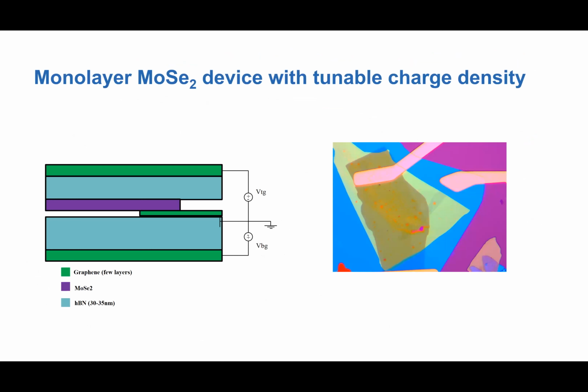Okay, so now an optical picture of the simplest device one can imagine. This is essentially a monolayer with top and bottom graphene gates. And we also have a graphene layer to contact the TMD. TMDs have large Schottky barriers, so it's very difficult to do transport with these. But if you have a graphene contact, you can use it, by changing the gate voltage, to control the charge density. The idea is that by using the top and bottom gates, if we increase them simultaneously, we keep zero electric field but change the chemical potential, moving it from the middle of the gap to the conduction band or valence band, etc. Or we could apply different voltages to the top and bottom gates and keep the chemical potential constant but change the electric field seen by it.